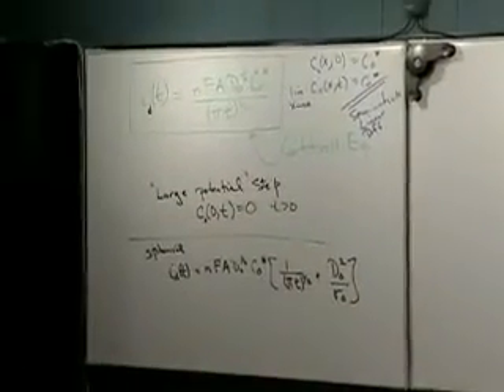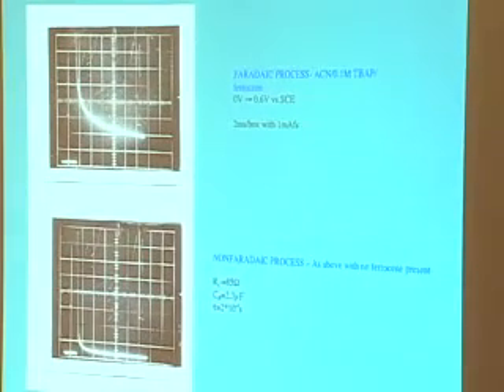And you can see two limiting situations here. Number one, at time equals 0, the Cottrell equation predicts that the current goes to infinity. Okay, that's a little hard to prove from this, but you will notice that it goes very high up. And if the Cottrell equation is right, that means that the current has gotten so large that your recording instrumentation and your tracking instrumentation, your potentiostat, aren't following it. So there's some very short time in here where you've lost control of the system. Okay, and then it falls down, and we expect it to follow this t to the minus 1/2 dependence.